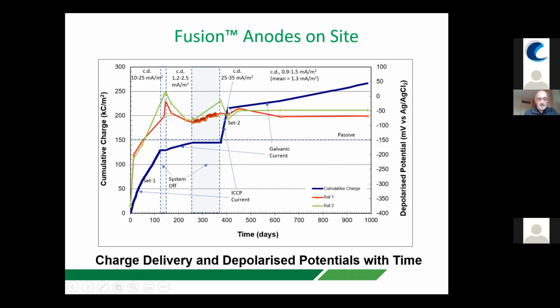They produced a charge as well. And this is the charge that's being produced by the galvanic anodes, which gives you a gradual increase of the charge delivery, which is the cumulative charge. Now, on the other graph, we have over here the depolarized potential, the potential 24 hours after each disconnection.